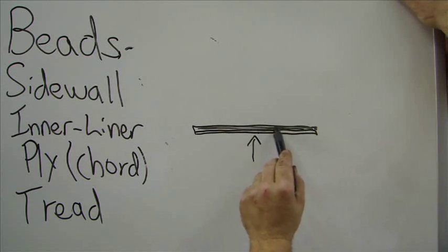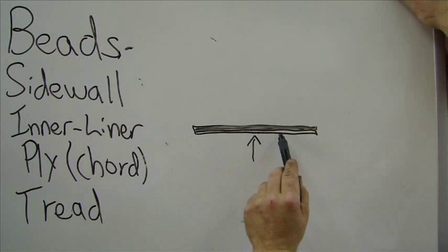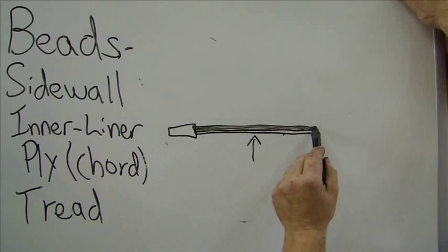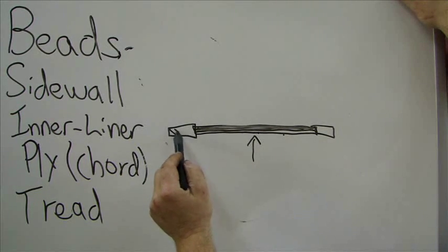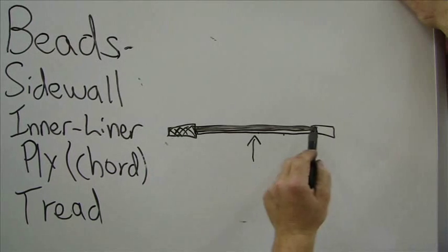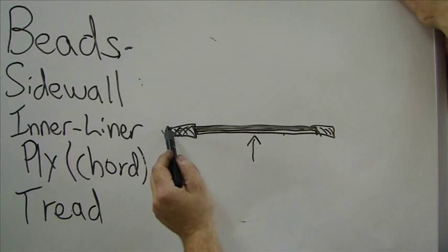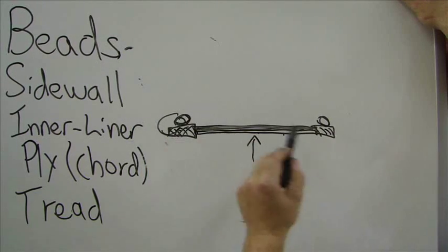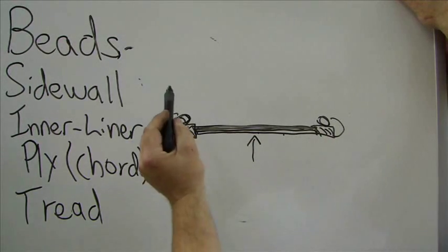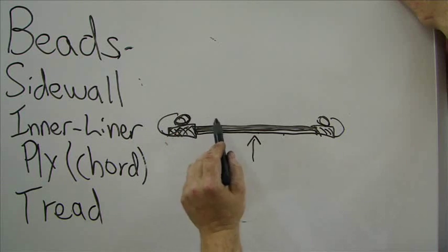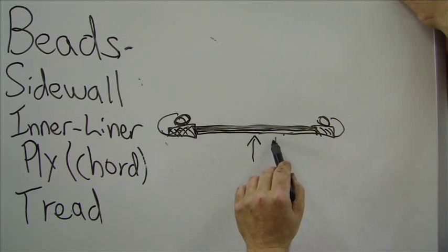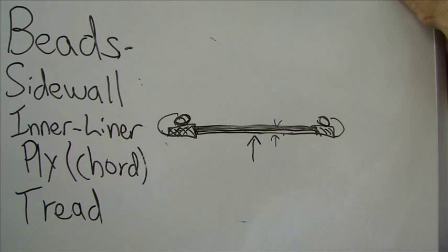Then on top of that is extruded another piece of rubber. And this is an adhesion layer. This is where it allows the inner liner to stick to the ply. On the outside of this, there'll be some chafing. It's called chafing. And that's nothing but a Kevlar ply that goes on the edge. And this is what gets wrapped around the bead. The bead is right here on each side. So this would get wrapped around, just like that. Now, we have the inner liner with the inner part, which prevents the air from going through, and the adhesion layer.